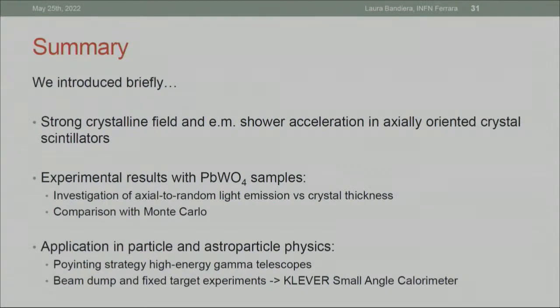So we briefly introduced the strong crystalline field and how the shower is accelerated in axially oriented crystal scintillators. And tests have been done with commercially available samples. So this effect is macroscopic, and we measured the enhancement of light emission with crystal thickness and compared it with Monte Carlo, in which we modified the physics list in Geant4.